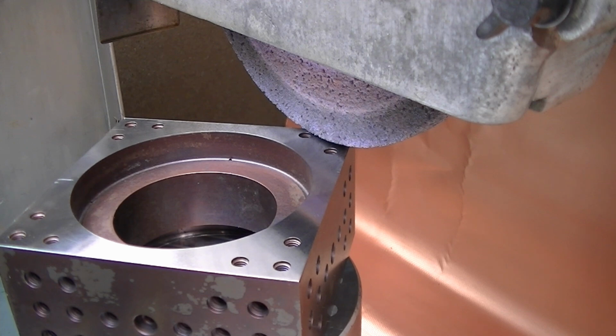Another important aspect to keep in mind when you're talking about very high precision grinding is, as you've heard me say many times, everything is rubber. The entire mechanical loop of this grinder, meaning from the grinding wheel back through the spindle, down to the column, over to the saddle, up through the saddle to the table, up through the actual rotary spin table and its bearings, all of that is the mechanical loop, and that has a certain spring rate, meaning if you push up on the wheel with a certain amount of force, you're going to get a certain amount of deflection, and also increasing the load on the table is going to have the table deflect some. So there's always deflections involved.